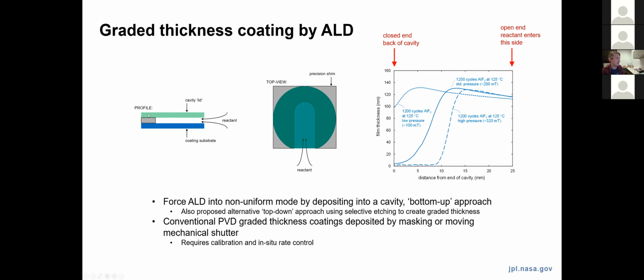You have your coating substrate on the bottom, and it's separated by a precision shim, in this case, some kind of mechanical apparatus to tune the height of some cavity to limit how far into the cavity the reactant can make it. This is a digital process, ALD, where you have these binary repeating AB cycles. And so you get this consistent introduction of reactant, purging, and then introduction of the next reactant, purging. And with the appropriate choice of the height of this cavity, you can create a profile that has this graded thickness effect. And so I'm showing on the right here some measured variation in film thickness as a function of distance into one of these cavities that we've used for testing, showing these profiles that can be generated.